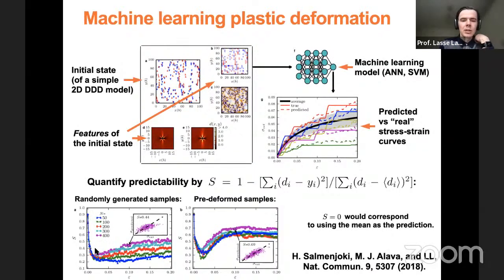But then this goes down quite quickly to relatively low values. And then, at least for large enough systems, it starts to increase again and reaches a plateau for large strains. So there's this non-monotonic predictability, if you like.